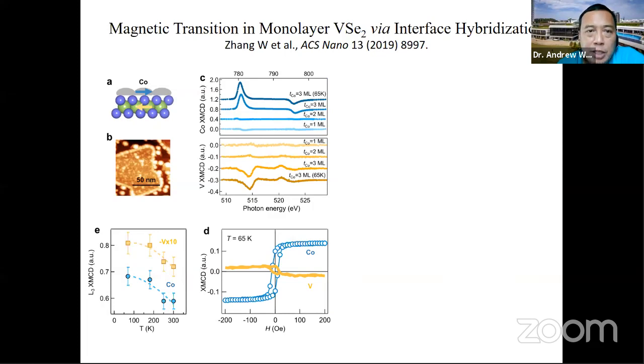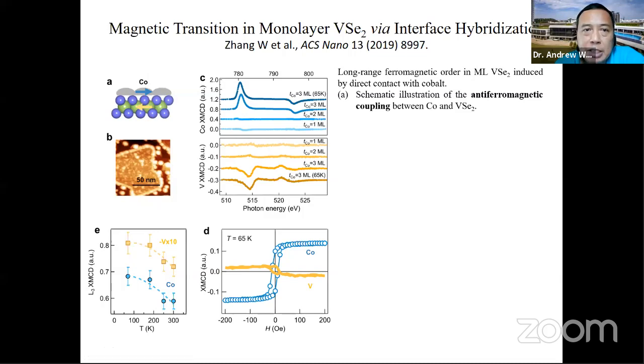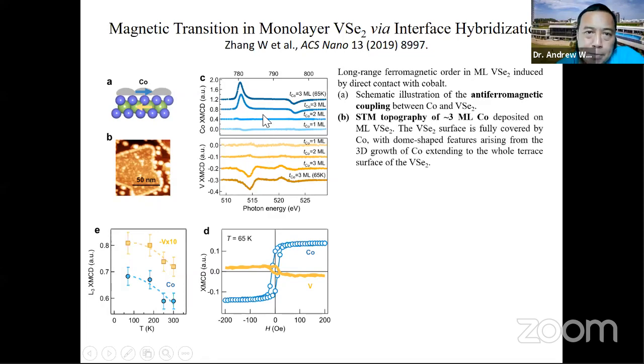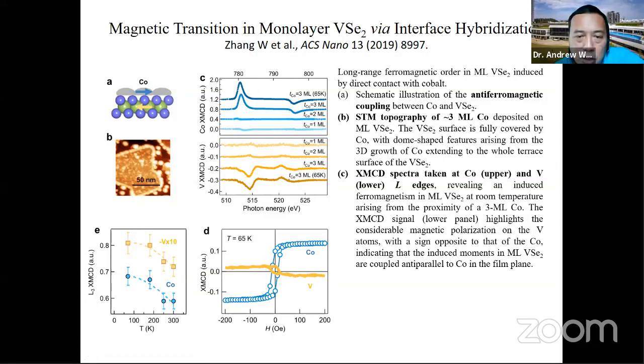Just going through the results, we can see that long-range ferromagnetic order is obtained and is induced by direct contact with cobalt. And you can see the schematic, there seems to be anti-ferromagnetic coupling because in the XMCD, the peaks are in opposite directions. STM topography shows that you have a fully covered vanadium diselenide surface with some islands of cobalt. And there, of course, is the XMCD spectrum showing clearly that you have the cobalt hysteresis and vanadium hysteresis anti-ferromagnetically coupled in opposite directions. And there's a temperature dependence of this dichroism.